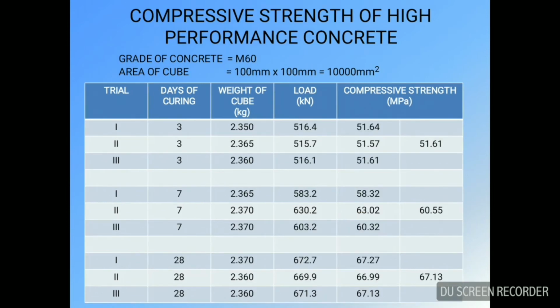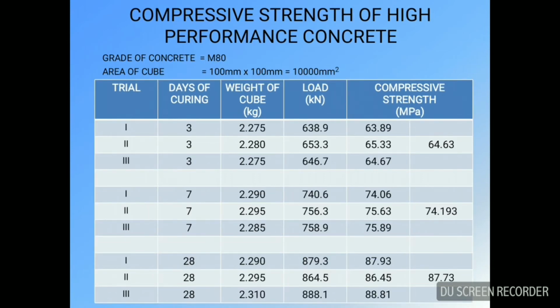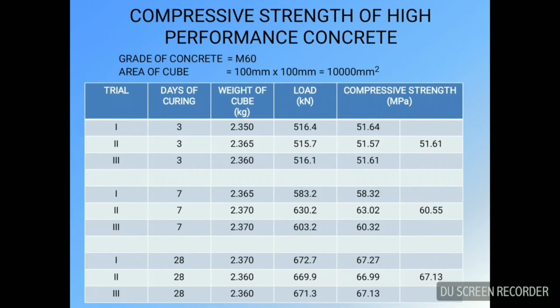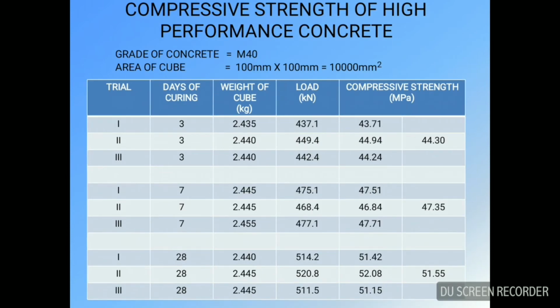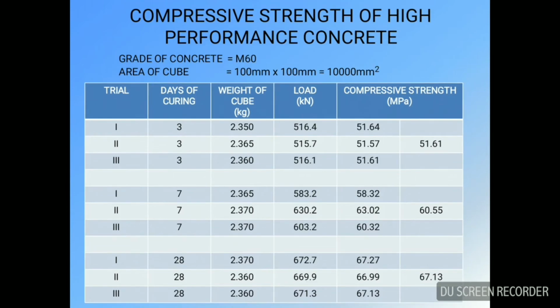Similarly, it was done for M60 also, with the same area of cube, same days of curing and 3 trials. At last we did it for M80 also, with a cube area of 100 mm by 100 mm and curing of 3, 7 and 28 days with 3 trials, with a maximum compressive strength of 87 at 28 days, and 67 for M60 at 28 days, while it was 51.55 for M40 at 28 days.